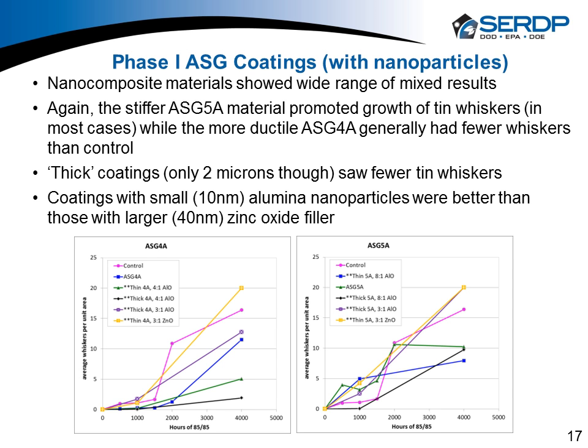But what we found is that if you put nanoparticles into both ASG5 or ASG4, it actually is better than just having the coatings without particles. Again, the ASG5 tended to produce whiskers faster than the ASG4. But we found thicker coatings are better than thin coatings, and coatings that had 10 nanometer sized alumina outperformed a 40 nanometer sized zinc oxide. In phase 1, we looked at alumina and zinc oxide, and the alumina did much better than the zinc. Some of that could be just zinc versus aluminum, but as you'll see in a couple more slides, we really think the particle size was playing a much bigger role than the elemental particle itself.